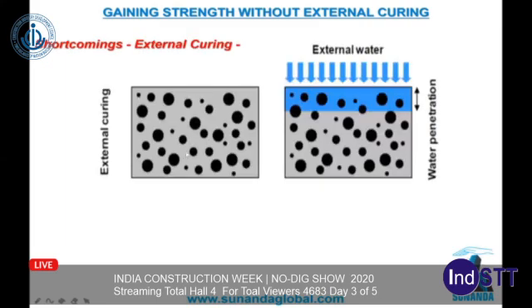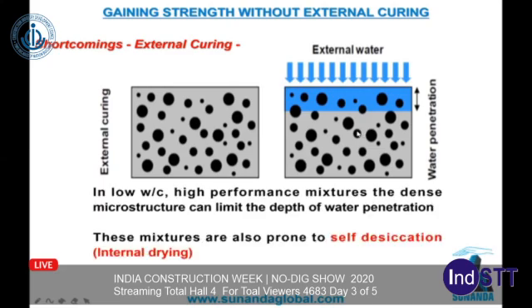What you see in the first two slides over here is external concrete curing. What happens is that water just penetrates inside and keeps the concrete in the hydrated form, and reduces the escape of hydration water from the concrete to outside. But again, it is subject to the errors that I mentioned earlier.